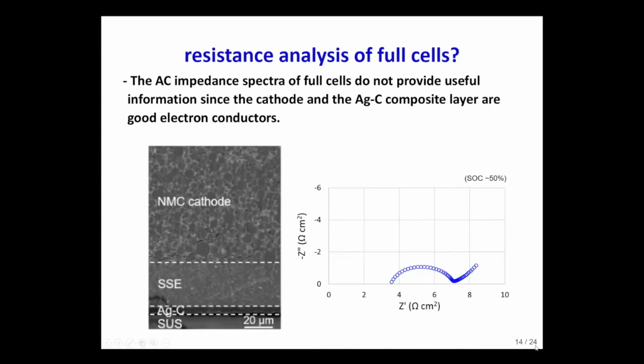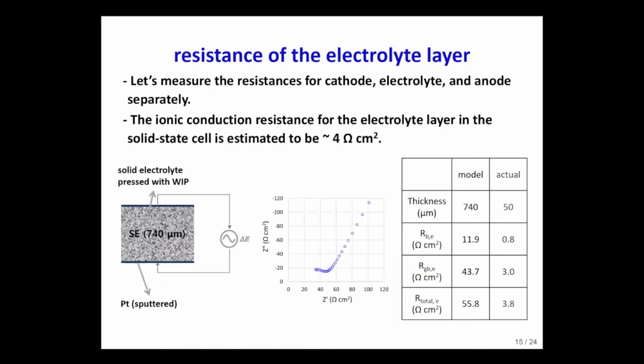As you can see on the right side, the actual Nyquist plot is very simple. It's very difficult to get the resistance information of each component separately from this plot. So we decided to measure the resistances one by one. All the data taken here from now on was taken at room temperature.